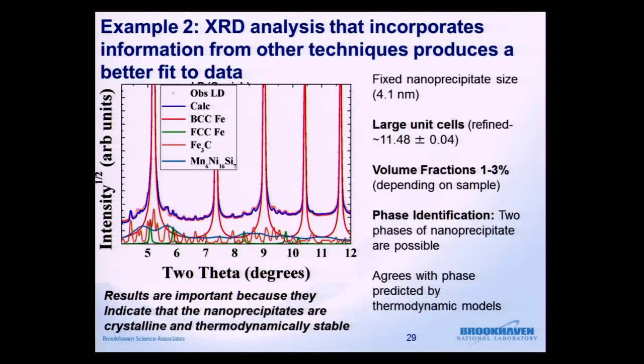Now the model is a combination of the phases that we identified in the material. So we have our BCC iron, our FCC iron, we have our cementite, and then we also added the nanoprecipitate phase. And this is this blue line. So you can see the blue line, due to the small size, has these very small, broad peaks. There's no sharp peaks from it, but it does contribute to the background, and it does have peaks. So this model, by including the nanoprecipitates, is a much better fit to the data than it is without including the nanoprecipitates.